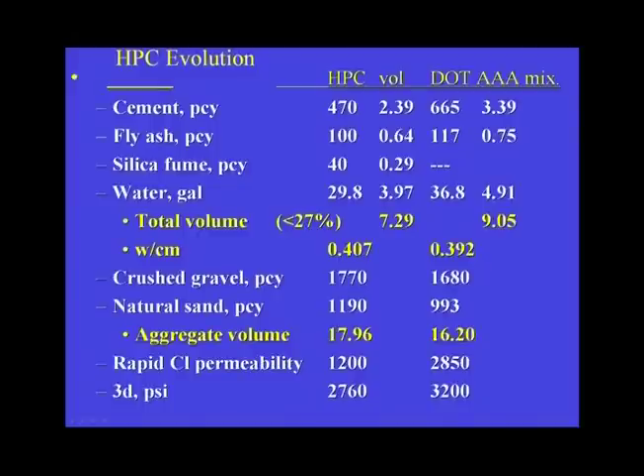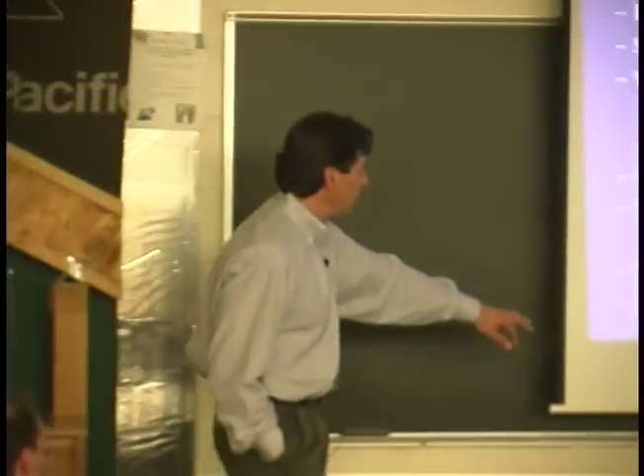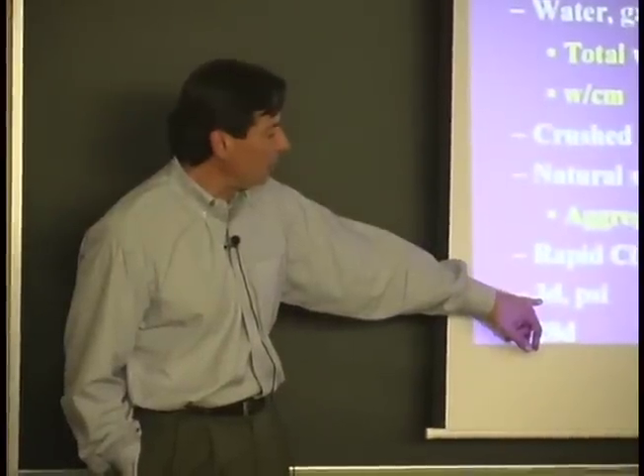and strength-wise, well, permeability-wise first, the high performance is a lot less permeable, but strength-wise, we see that the materials catch up at 28 days, that the strengths are basically the same. At 3 days, there's a little bit of lag here, but that's actually good for cracking on a bridge deck. When they ran this thing out to 56 days, this strength went up to over 6,500.